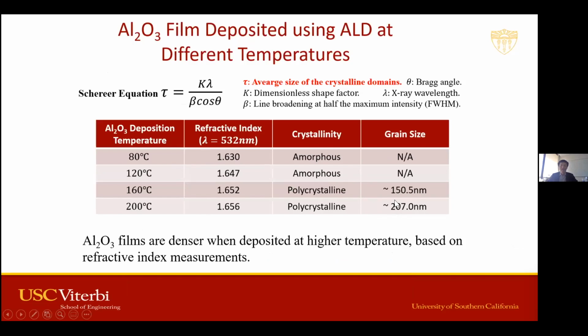One is deposited at 160 degrees C, and the average grain size is about 150 nanometers. One is deposited at 200 degrees C, and the grain size is about 207 nanometers. We also measured the refractive index, and you can see when it was deposited at a higher temperature, the refractive index gets slightly higher. That basically means the material is getting denser.